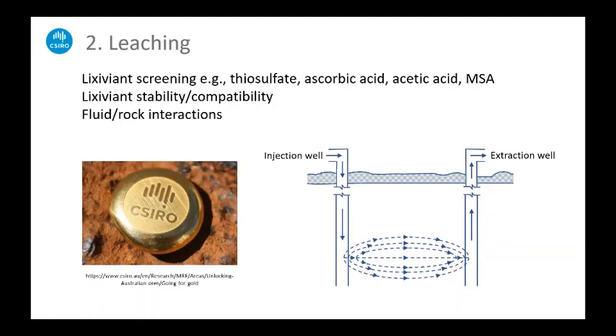We've also looked quite a bit at lixiviant stability and compatibility. So if you look at the image on the right, you've got the injection well, the fluid moving through the deposit to the extraction well, and you don't have the opportunity between the injection and the extraction well to control solution conditions. So you can't adjust your pH, you can't adjust solution potential. There's the potential that if the conditions are incorrect, you either precipitate dissolved value or generate other precipitates that could block flow, for example. And just as another point, the injection and the extraction wells can be spaced up to 20 meters apart. So it's quite an extensive distance often that you'll be pumping fluid over.